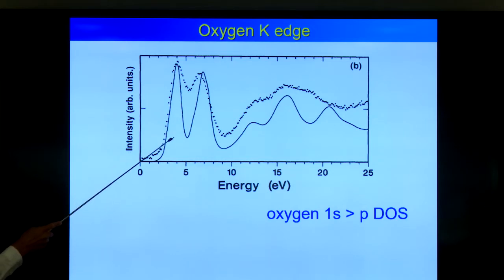What happens if you put a full core hole? Then the intensity of the first peak drops. So you get a better description of your peak positions with the core hole, but the overall agreement with the experiment in intensity goes down, and you can only solve that. I think it has only been recently solved by David Prendergast's calculations, because you should not put a full core hole. You should fit your core hole potential to the final state. And if you do that, then you get a complete description. So the really detailed, accurate description is much more complicated, but you get 90% of the ground state density of states.